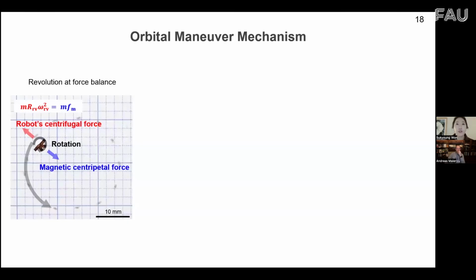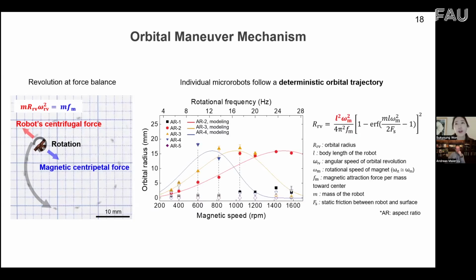The rotation and revolution of the microrobots result from the force balance between the centrifugal force of the rotating magnetic robots and also the magnetic centripetal force from the permanent magnets. So we can expect their trajectory, because the orbital radius of the microrobots is determined by the robot body length and the magnetic frequency based on this force balance equation. So we can tune their trajectory and the actuation mode by adjusting these factors.